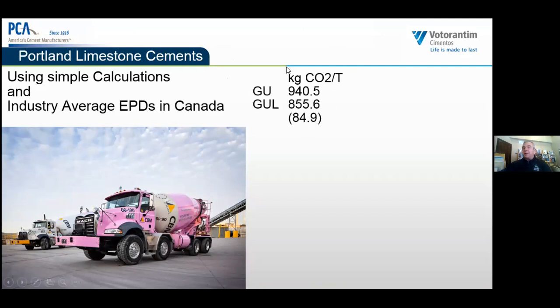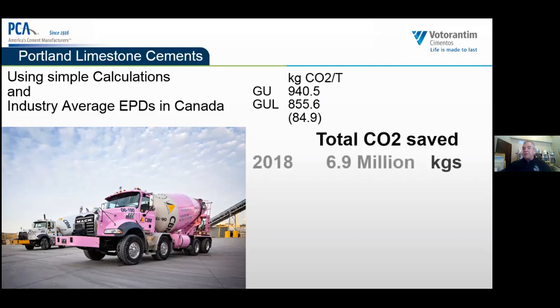If I use the EPDs, Environmental Product Declarations, from the Cement Association of Canada, we did establish an industry average of CO2 per ton for GUL and GU, and the difference being 85 kilograms of CO2 per ton of cement is a differential. And I just basically took the numbers that CBM has used over the past 3 years, and CBM, in their usage of GUL cement, basically saved 6.9 million kilograms of CO2 from going up into the atmosphere.